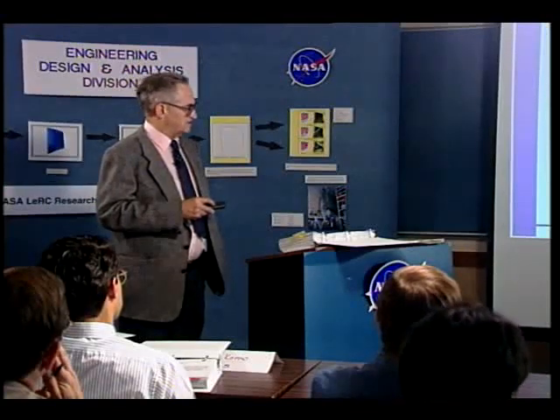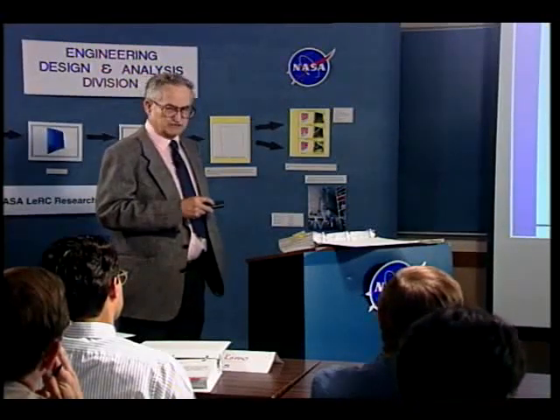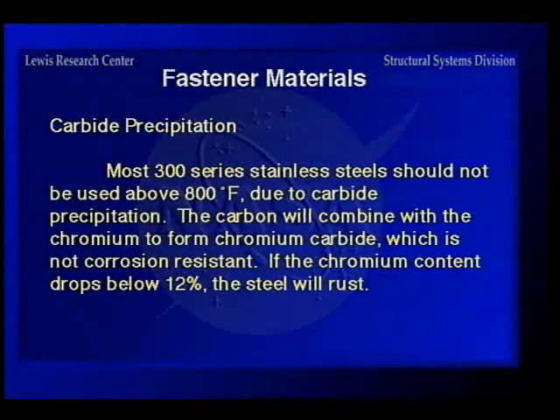solution treat it after welding, which means you take it up to about 1800 degrees or something like that and get the chromium back in solution. Because what happens, the carbon will combine with the chromium to form chromium carbide in the weld joint, and of course that pulls the chromium out. So if you had your regular 304, which is an 18-8, 18 chromium 8 nickel, you pull the chromium out. If it falls below about 12%, the steel rusts.